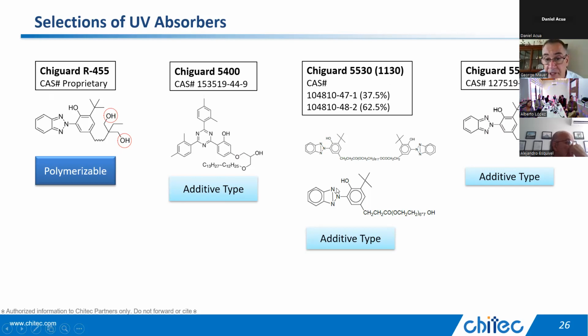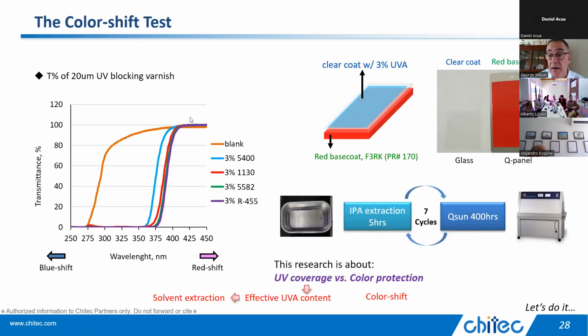The 1130, this fraction of the 1130 mix can graft in, it doesn't polymerize in. But in a way that doesn't matter because this linkage here is weak and can break down, so it's not so great that it reacts in. Just like this linkage here breaks, and then the 1130 goes away. And the 5582, it's a smaller benzotriazole, so it's not as permanent as some of the big ones, but it's a pretty good molecule. But it does not react in. So in a really difficult, stressful situation, we wouldn't expect this to be as good as the R455, which polymerizes into your system.